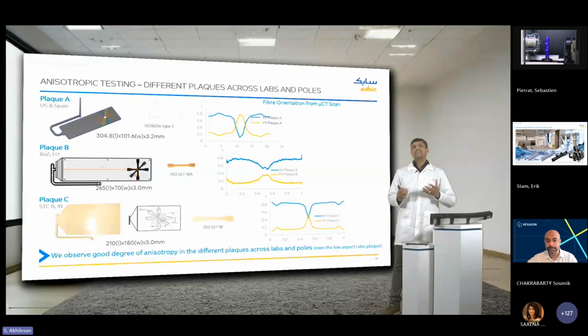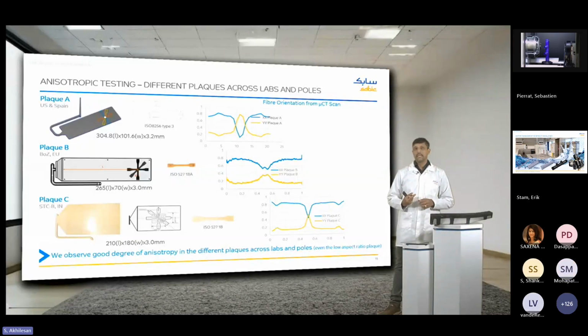There are different plaque geometries that different labs follow, as you can expect, right? So you'll see different geometries that I show on the screen. What at SABIC we do is to make sure that we study the anisotropy in any of these plaque geometries and ensure that at the locations where we cut the specimens and test the properties, the fiber alignment is well defined in the flow direction. That's the first step. Now let's take a look at what measures we need to take while carefully injection molding such shear plaques.